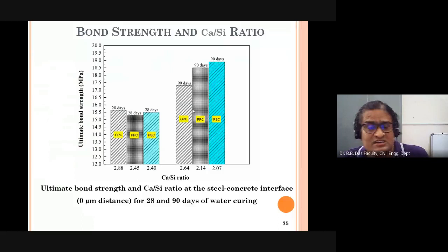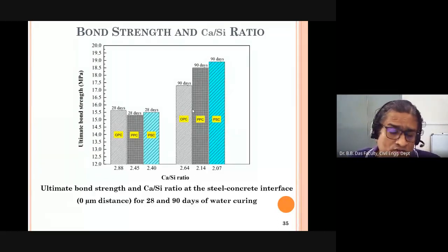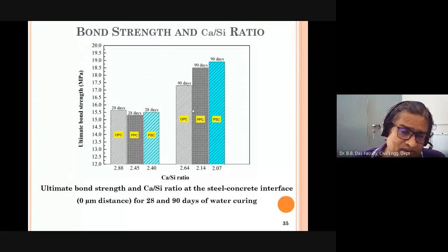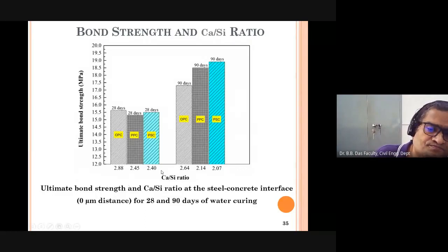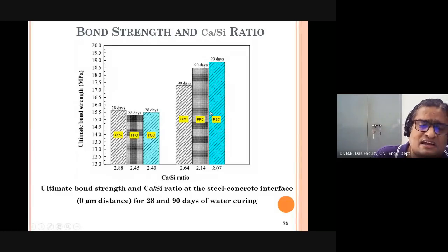And whatever the bond strength, I have talked about the same specimen. We just did the bond, meaning we pulled the steel from the concrete. Here, the Ca by Si ratio and the ultimate bond. You can see here, this is for 28 days, this is for 90 days.